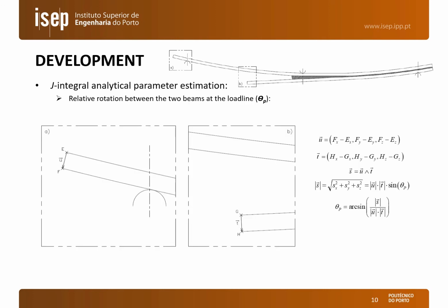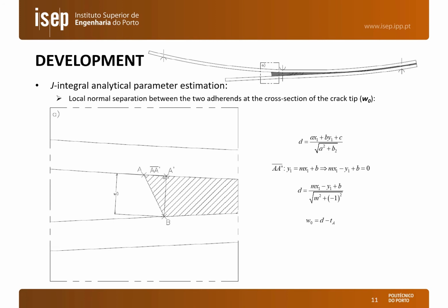Regarding these parameters, beginning with theta p, we obtain this parameter by calculating the angle between two vectors, the vectors EF and GH, which gives us the rotation between the upper and lower adherends. Regarding the normal or the tensile separation, we considered the perpendicular distance to a tangent to the line AA', such that we obtain w0, and then this w0 is the opening minus the adhesive thickness.